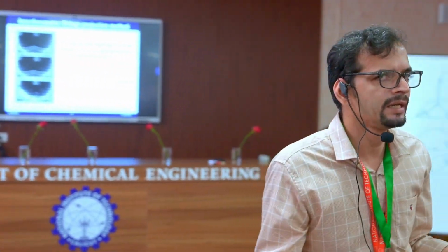And this you can translate, because if you know the refractive index and the other parameters, you can make a calibration curve of how much bending corresponds to how much contact angle. So it's a very precise method. We published that in Langmuir. Dilip was working with very low contact angle systems and it was really successful. We did it in our lab and we also did a setup at IIT Madras.